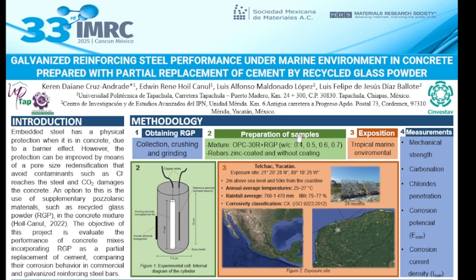In the second step, the sample preparation, concrete samples were prepared using only OPC 30R for the blank samples and OPC 30R plus a partial replacement of 10% of RGP for the experimental samples. And the 2 types of samples were divided in 4 water cement ratios of 0.4, 0.5, 0.6, and 0.7. For the corrosion test, concrete samples were prepared embedded with 2 types of reinforcing steel rebars: rebars with zinc coating and rebars without coating. And the experimental cell was left as shown in figure 1 in this case.